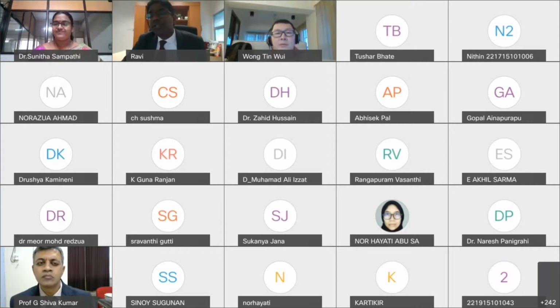Thank you, Dr. Zahid. Sorry, I'm interrupting again, Dr. Ravi. Sometimes Ostwald ripening is also because of high PDI. I just noticed the PDI was also high, which also might be because of the low pressure that you are using in the high pressure homogenizer. So maybe you can increase the pressure slightly. That will also reduce the PDI and avoid the problem of Ostwald ripening in your suspension.